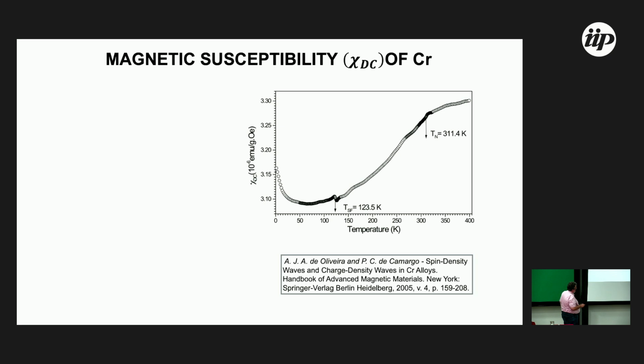At 123.5 K, the spin flip transition is a small jump here. And increasing the temperature to TN, 311.4 K in my sample, above this temperature is the spectrum of the Pauli paramagnetism. The spectrum of the metals, the spectrum of the chromium. Okay?